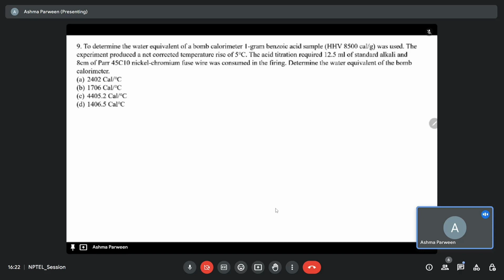So we have to determine the water equivalent of a bomb calorimeter in which 1 gram of benzoic acid sample was used. The experiment produced a net corrected temperature rise of 5 degrees centigrade. The acid titration required 12.5 ml of standard alkali, and 8 centimeter of Parr 45C10 nickel chromium fuse wire was consumed in the firing. We have to determine the water equivalent of the bomb calorimeter.